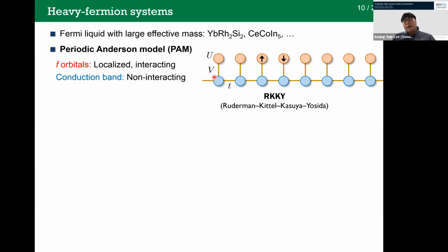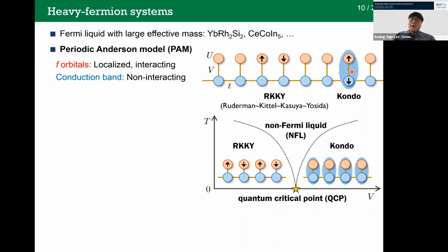In this system, there are two mechanisms competing with each other. One is the RKKY interaction, which favors antiferromagnetic correlation of the f electrons when the conduction band is near half filling. And the other one is the Kondo screening. And this Kondo screening sensitively depends on the value of V. So when V is large, the conduction electrons come to screen this f spin. So when it is screened, then neighboring f electrons cannot see this f electron spin. So then the RKKY interaction cannot hold because there is no target to make the anti-alignment. So the system will be in the Kondo phase when the temperature is low and V is large.